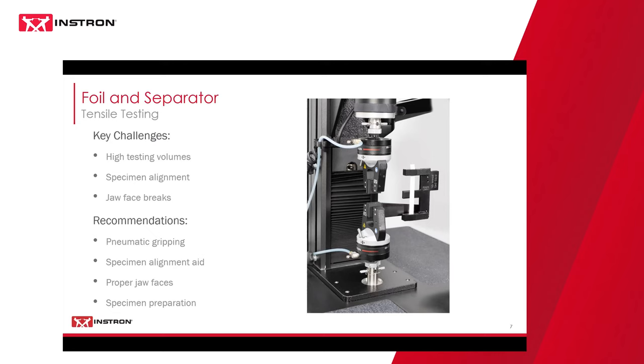Products like shown to the right here, this is Instron's precision specimen loader. It's an example of an aid that can be used in these cases. It's highly recommended for both these materials, given the delicate nature of them. Having an alignment aid like this or an insertion aid can help reduce the operator dependence and the variability and also help increase throughput. This example shows the specimen loading device. It has a detachable fixture that holds your specimen and then a mating fixture that's attached directly to the grip. So it ensures both proper alignment and proper insertion of your specimen every single time. Again, this comes back to the operator dependency and variability that can occur, especially when you have personnel turnover.